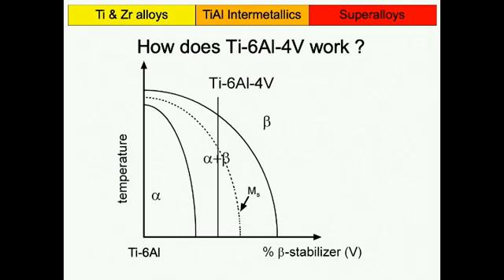So when you think about thermomechanical processing now, what I want you to realize is that depending on the temperature at which you forge or roll the material, you actually have different fractions of alpha and beta phase. And that has a very pronounced effect on the microstructure you generate and the crystallographic texture you generate in your material. You can also even thermomechanically process the material up here in the single phase regime. And that's also done at certain stages.